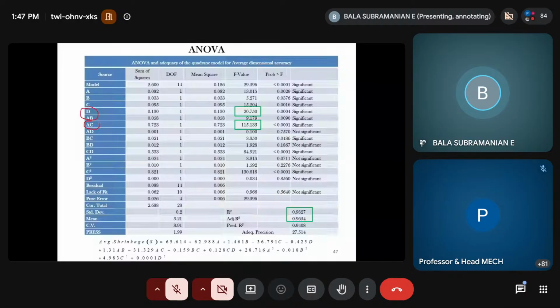So we have used here the desirability approach, and then we have investigated surface roughness and the same aspects. And then we have used here the gray relational analysis algorithm. Okay, so then we did some AFM measurements to measure the surface quality based upon the surface roughness, optimal process parameters, printed process parameters. Okay, and then we have done some analysis for understanding the vibration characteristics, dynamic mechanical properties, and these are some observations for loss modulus. Loss modulus is nothing but energy dissipated as heat, and storage modulus is energy stored during the application. Okay, so this is the important profile for the vibration aspect.